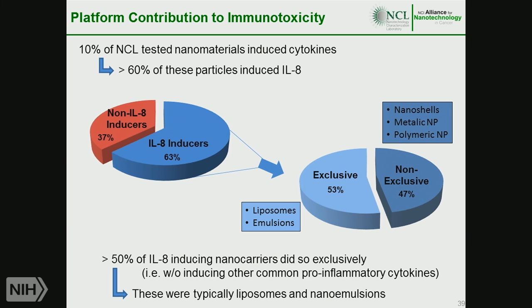And the common denominator between these materials was their composition. Materials that induced interleukin-8 without induction of TNF and IL-1 were liposomes and emulsion. And Anna Ilinskaya in my group did the mechanistic study to show that this induction of interleukin-8 is related to oxidative stress, which did not involve gene expression, but involved protein expression from the pre-existing mRNA. Basically, oxidative stress led to stabilization of the low levels of mRNA that mononuclear cells maintain, and resulted in expression of the protein from this mRNA pool, which was very interesting.